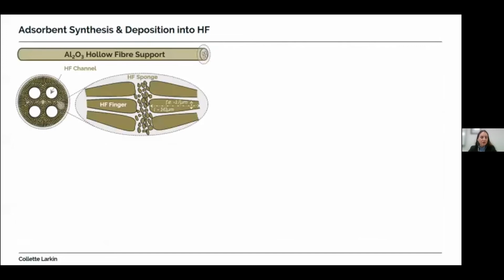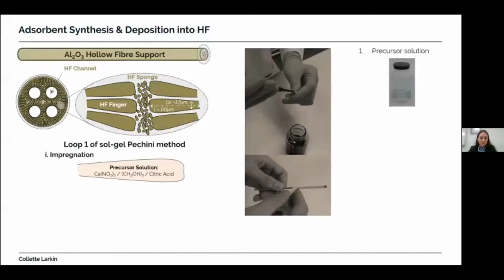So once we have our alumina hollow fiber supports, we can deposit the adsorbent material inside the fingers. In this work, we selected calcium oxide as the adsorbent material, since it is a cheap and widely researched CO2 capture adsorbent. The sol-gel Pechini method was employed to deposit the calcium oxide. The first step of the method was to make the precursor solution, which was pipetted into the hollow fibre. The outside was covered using Teflon tape to ensure only the inside of the hollow fibre was impregnated.